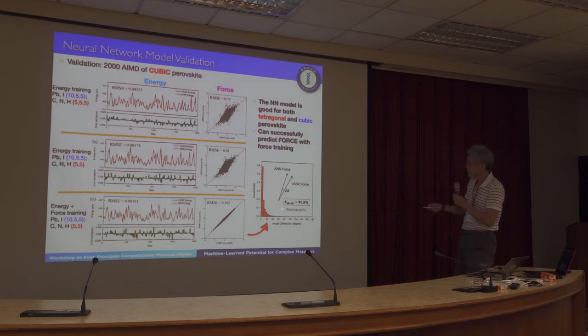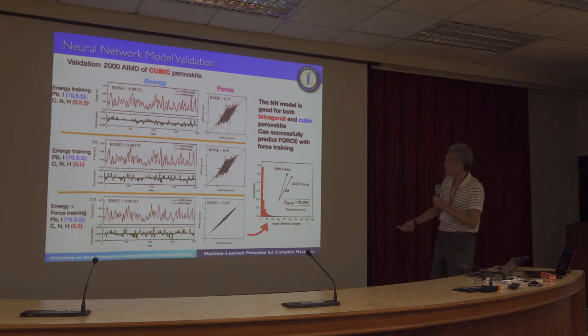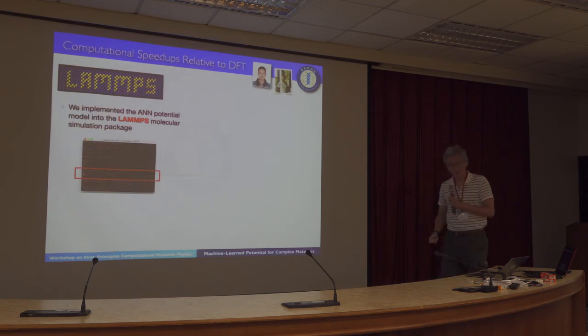We also compute the direction parity. This is the angle difference between the VASP force and the force predicted from the neural network model. You can find that 91% of the forces predicted are within a 20-degree difference compared with VASP. So even the force direction is very good. So we know that the neural network potential model can basically reproduce the force and the energy from VASP. But what about the benchmark? I mean the computational speed.